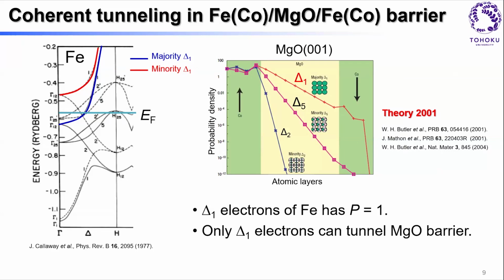So this was proposed by two theory groups, Bill Butler and Jaafar Mathon in the US and in the UK, that when you build a crystalline structure oriented 001, then the decay of the different symmetry wave functions is extremely different. Meaning that if you construct this thing, then when you're looking from the right-hand side inwards, you only see delta 1 coming out, and delta 1 is actually, even in the spaghetti-like band structure in iron, a half metal, or 100% spin polarized.